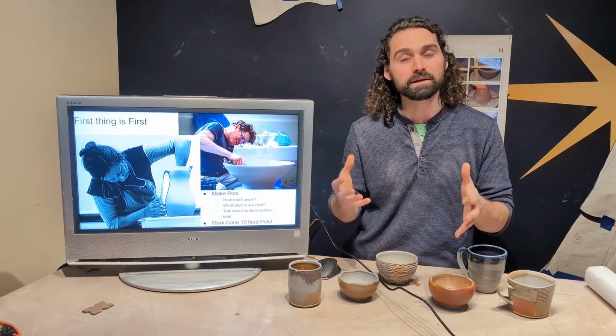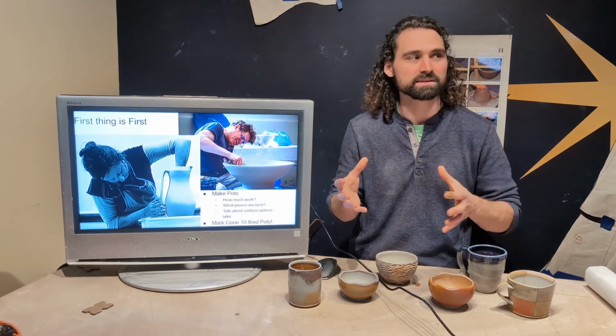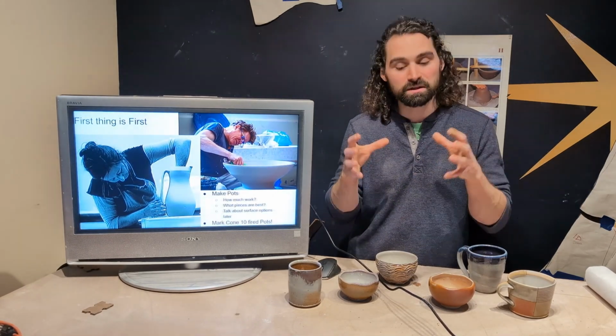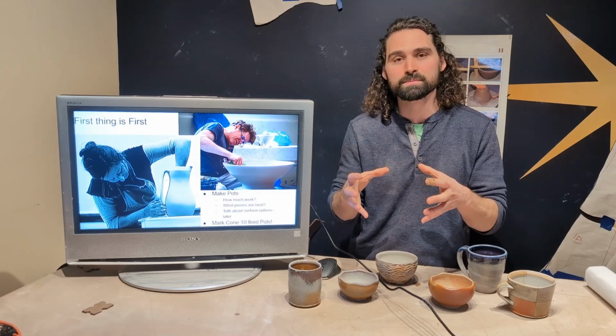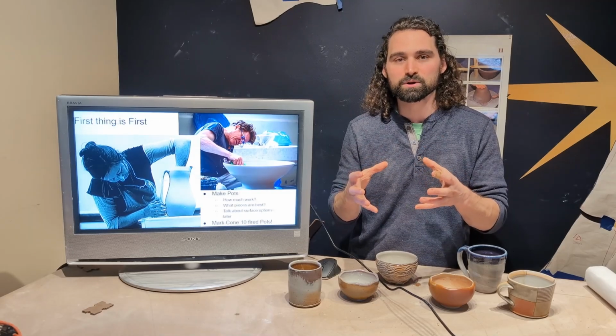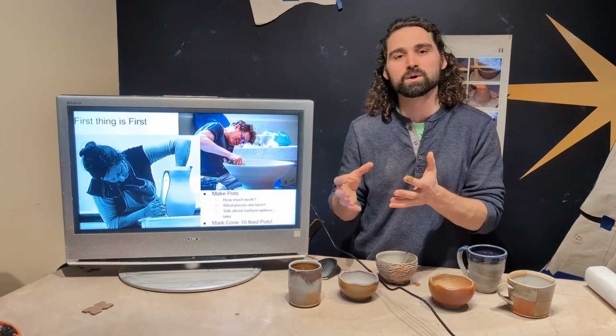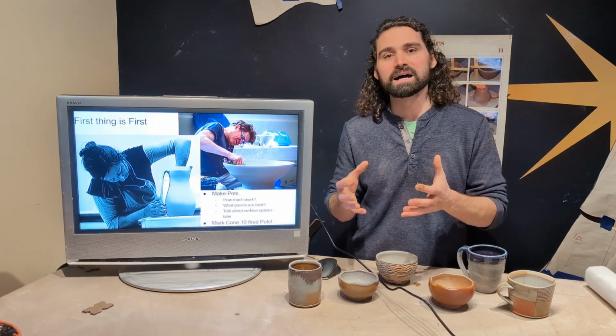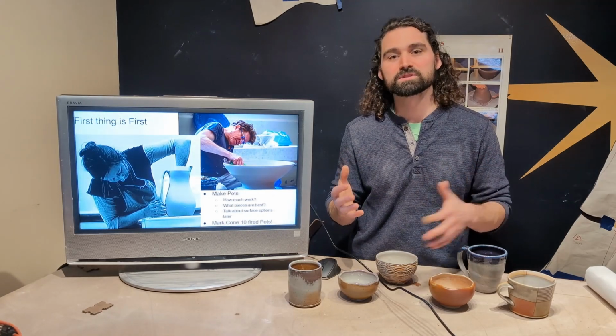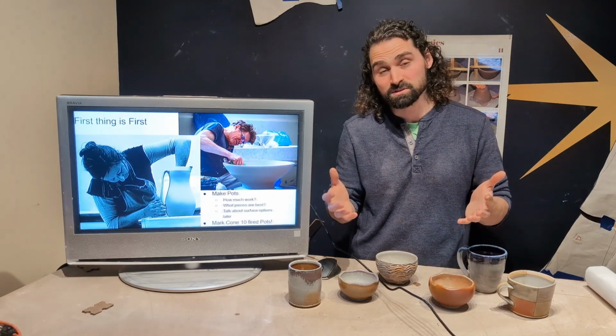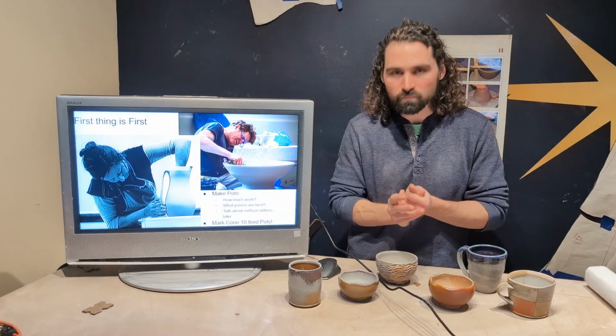So I would really recommend marking your pots differently so that you're sure that those pots are the pieces that you made with your cone 10 clay and not accidentally a cone 6 body or lower that's gotten in. It's very hard to tell the difference after they've been misfired. Sometimes it's hard to tell while they're still wet.